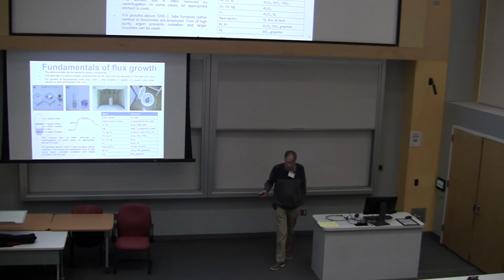The furnaces: this is looking at the inside of a box furnace. This is a silicon carbide furnace. These are silicon carbide rods. Silicon carbide furnaces operate up to about 1500 centigrade. These are fine for these kinds of quartz operations to 1200. The lifetime of these elements, which actually aren't so cheap, is greatly reduced if you work near 1500, and a lot of the high temperature furnaces now use molybdenum disilicide elements, which last longer and can actually go to higher temperatures.